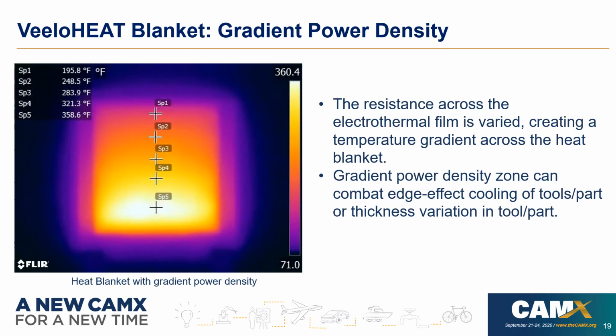This shows a blanket with a gradient power density. This blanket was actually a pretty recent design. We were able to tailor the resistance across this film and actually achieve a gradient temperature profile. This was developed for a customer who had issues combating edge effect cooling of their part caused by just natural cooling or just thickness variation.